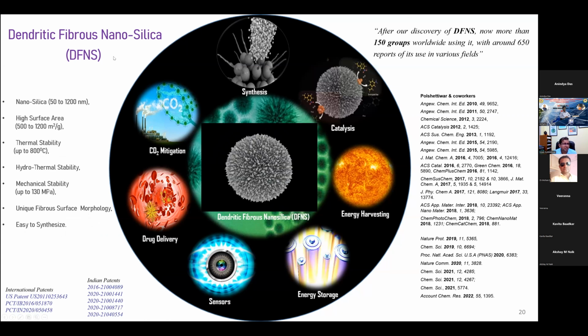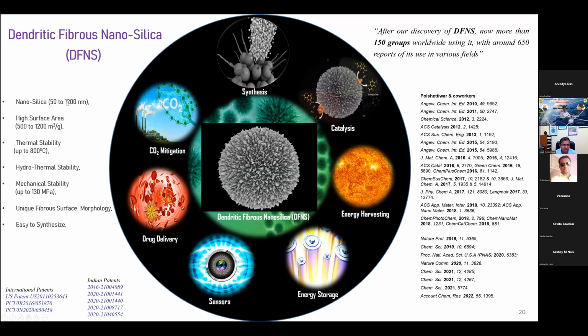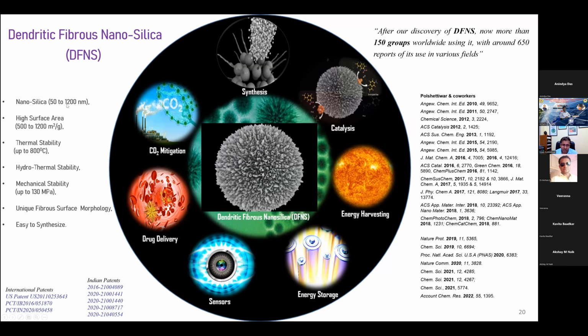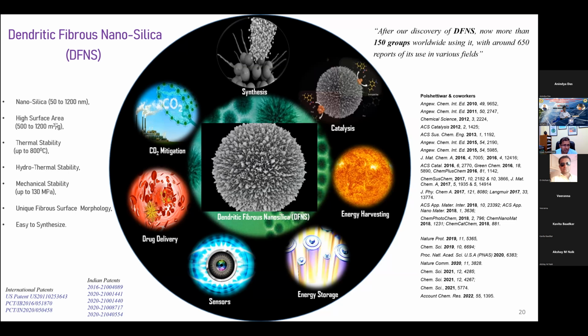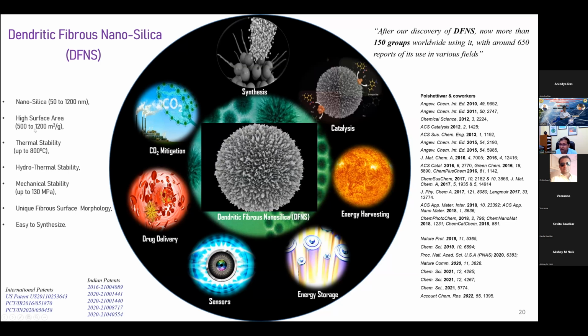So this is one of the examples. This is a nano silica. It has a dendritic fibrous morphology, we call it DFNS. The particle size can be tuned, from 50 to 100, 100 to 200, up to 1200 nanometers. Based on the application, we generally use different sizes. It has a huge surface area, 500 to 1200 meters per gram.